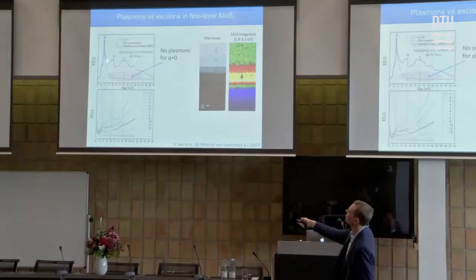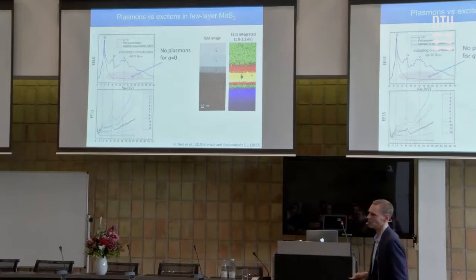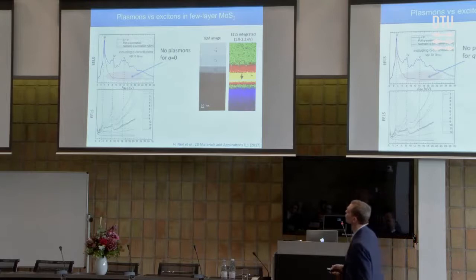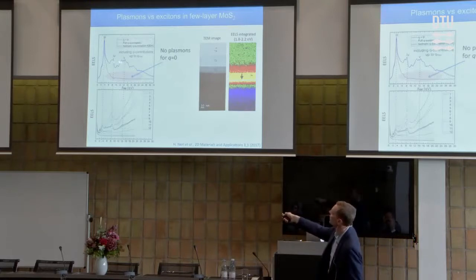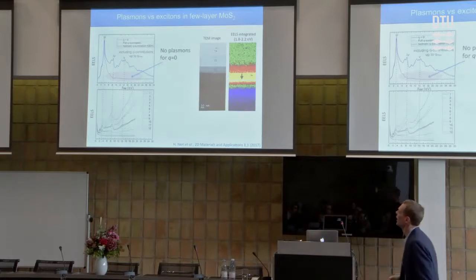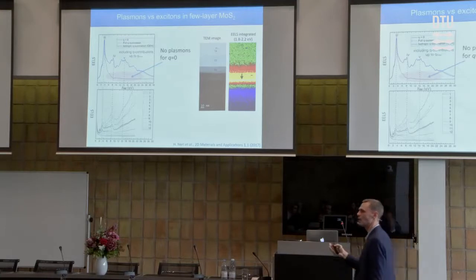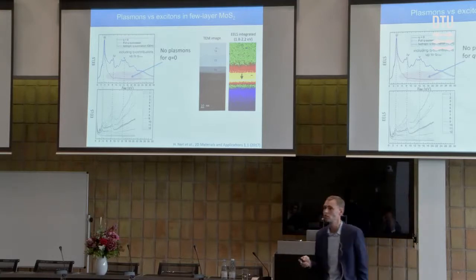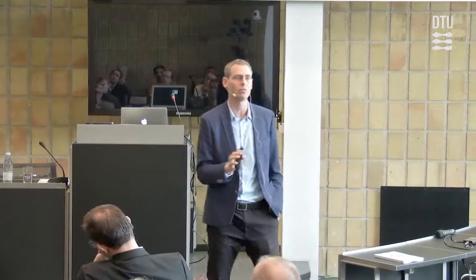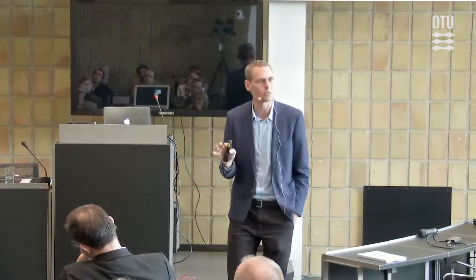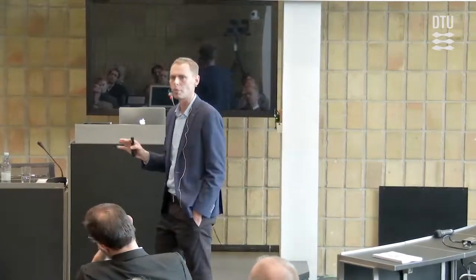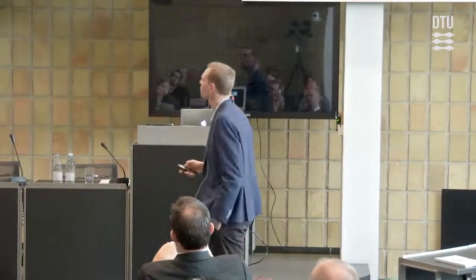And you can see now we get a very nice agreement—well, a better agreement, for sure—with the experimental spectra. There is still a lot of room for improvement, but we get these features, and they are indeed due to the plasmons. The plasmons develop at finite Q, so they are completely absent for Q equal to 0. That's very different from the three-dimensional case, where plasmons typically dominate the EELS spectrum for Q equal to 0.